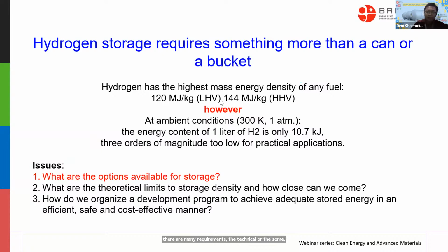This number I already mentioned before, the LHV and the HHV of hydrogen. However, at ambient condition, about 27 degrees Celsius and 1 atm, the energy content of 1 liter, meaning a very huge volume, of hydrogen is only 10.7 kilojoules. So the order of magnitude is too low for practical application. It is not ideal for practical applications, and there are some issues that we need to overcome.